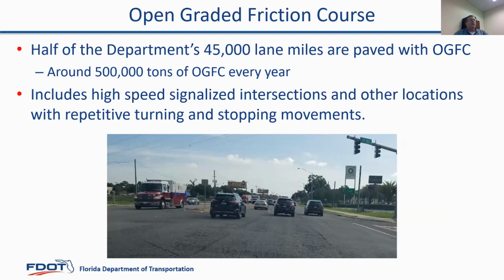We use a lot of open graded friction course in Florida. In fact, half of the department's lane miles are paved or surfaced with open graded friction course. So we're doing around 500,000, maybe a little bit more tons of open graded friction course every year. And we tend to put it in places where most people would cringe, like that picture shows there. That's a signalized intersection at 45 miles an hour at an interstate interchange. But again, the concern there was hydroplaning because we get a lot of heavy rain in Florida. And so the designer chose to use an open graded friction course, and you get the result you would expect, a lot of raveling. So we want the safety. Safety's number one. And so we want to make the open graded friction course more resistant to raveling.